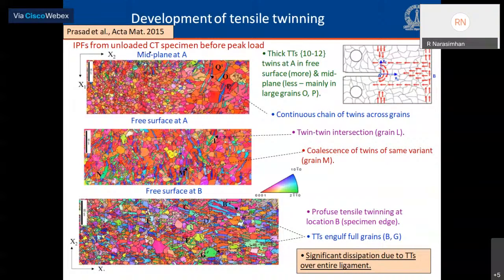Specifically, if you look at the top IPF, you can see there is a continuous chain of twins cutting across grain boundaries. For example, close to grain Q at the top IPF, you can see a chain of twins which are extending across multiple grains. The middle IPF shows intersection of twins in some grains. For example, in grain L, you can make out intersection of two twins. And coalescence of twins of the same variant in some grains, for example, grain M in the middle IPF. The bottom figure shows some of the grains having completely been engulfed by tensile twins, for example, grain B and grain G. So this establishes the significant dissipation happening because of extension twins over the entire ligament.